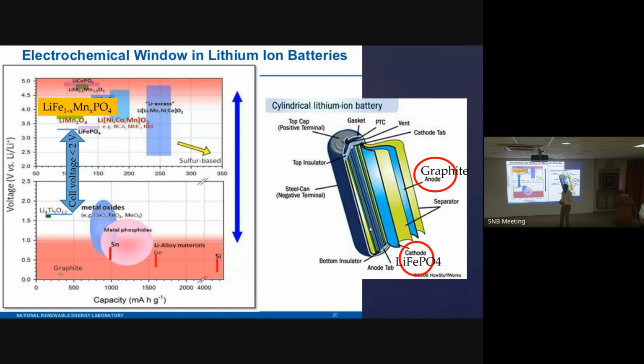The kind of granularity, everything matters. Morphology matters a lot. Here what is required is nanoparticles, but the tap density should be very high. So what we do is granulate them. That means billions of particles we make like a glass. Actual particles are micron size only, but each micron size particle contains hundreds of nanoparticles, thousands of nanoparticles.